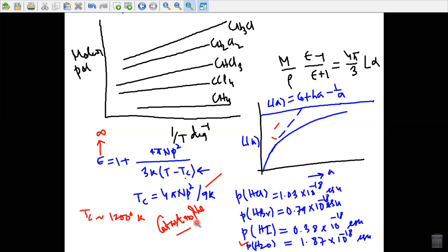Onsager pointed out that the theoretical basis of the Lorentz field, from which the catastrophe stems, does not include the case of permanent dipole moments, as here the moments are not in general all parallel, as assumed in the discussion in terms of E2 and E3 in the local electric field.